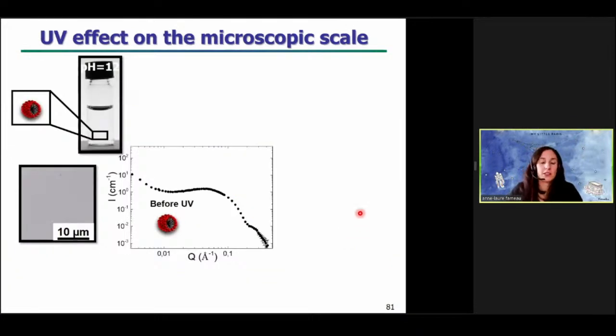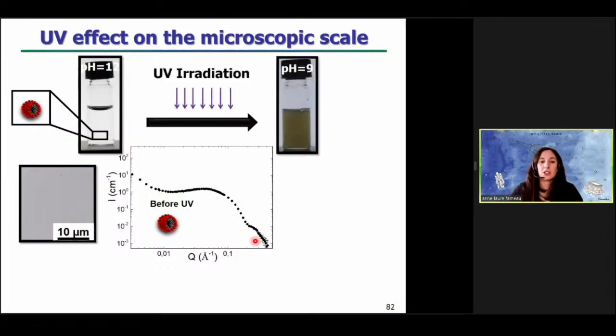For this study, we start with a solution of fatty acid at a low pH, pH 1. So we have spherical micelles inside the solution. As you can see here, we have a limpid solution. And by SANS, we can clearly see that before UV radiation, we have very nice spherical micelles. Then we put this sample under UV radiation, and we observe an increase of the pH from 1 to 9, and a transition at the macroscopic scale from a limpid solution to a turbid solution with a slight yellow color.